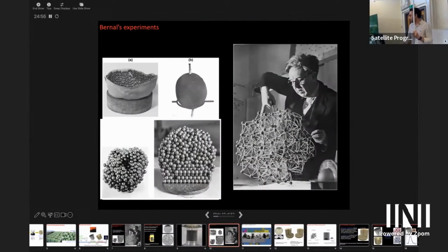Again, the hard work that Bernal and his team did is really remarkable, and I appreciate it really deeply after I tried to reproduce some of that. They actually poured bitumen. They created these packing structures in some sort of flexible membrane, and put a lot of steel beads in them, while making sure that you don't create a lot of order. They went through a lot of processes, and then they poured very gently bitumen into this membrane, and once everything was cool and cold, they removed these beads one by one, and looked at how many contacts there are on each bead, wherever bitumen wasn't touching, right? And then they reconstructed this structure from that. And they did more than one. That's really a lot of work. And I feel sorry for the students who did that and whose names didn't appear on the paper.